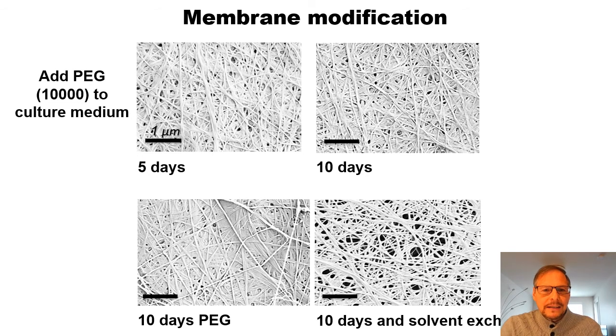As an example of in situ modification, if we let the bacterial cellulose produce the cellulose ribbons, the BNCs, this is what you see here. But if we do that in the presence of a polymer in the culture medium, in this case PEG, polyethylene glycol with a molecular weight of 10,000, then the film that will be formed can be adjusted depending on the presence of this molecule that we have added. So here we have the case of incubation for 5 days and for 10 days. In the top row, you can see how the pellicle or the biofilm or the membrane becomes more dense just by letting the bacterial cellulose produce more and more cellulose ribbons. In the bottom, you see exactly the same, but in the presence of PEG, after 5 days and after 10 days.